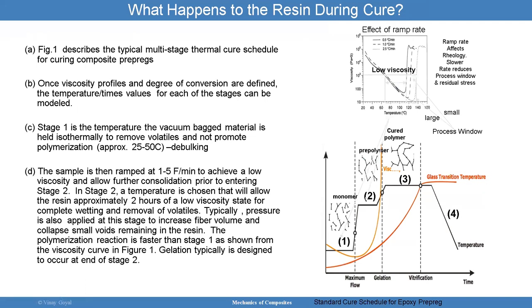So I wanna really go into the nuts and bolts of what is going on to the resin, what's happening to the resin during cure. And I have a figure here on the right side showing that. What I'm showing here is time, and temperature. So this is what I call a multi-stage thermal cure schedule for curing composite prepregs. And you may say, okay, I'm increasing temperature, then I'm dropping temperature. So you can see it's not uniform, it's not constant. And there's a reason for that.